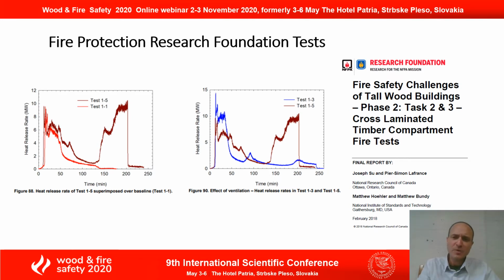It decays a little bit more slowly when there's the exposed CLT, but towards the end of the test, we have what's called a delamination, which led to fire regrowth. And that's when the CLT loses a layer of adhesive, or the adhesive fails before the char reaches the adhesive bond line, and that drops fresh fuel into the fire, and that caused fire regrowth.